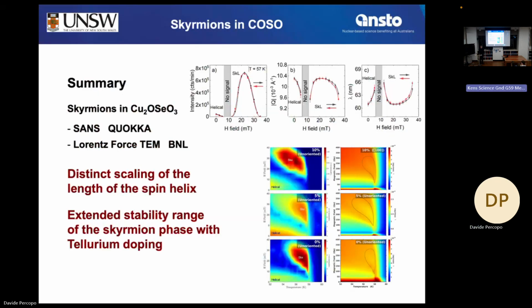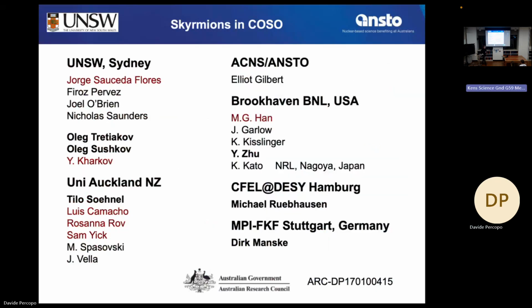Yeah, and that's the summary of my talk. We confirmed that we have skyrmions. We measured their length scale and how we can manipulate that with temperature and magnetic field. Highly important for industry applications to know that. And we used tellurium doping to change the skyrmion stability range.